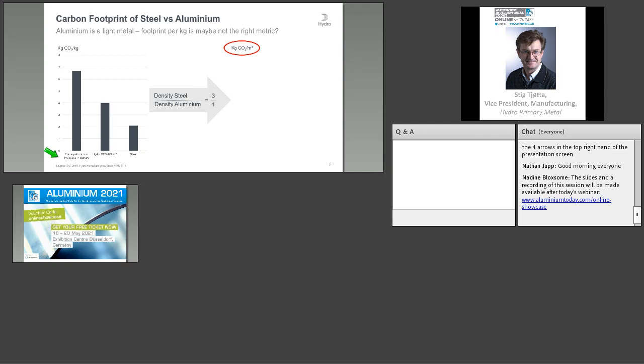So instead, if we look at the carbon footprint per volume unit of material, the picture changes quite drastically. Then we have that primary aluminium produced in Europe has a footprint more or less similar to steel, while aluminium based on renewable energy sources will have a significantly lower carbon footprint. Now, in reality, we seldom take out 100% of the weight saving potential, replacing 1 cubic meter of steel with 1 cubic meter of aluminium. So in practice, it will be somewhere in between these two extreme cases.